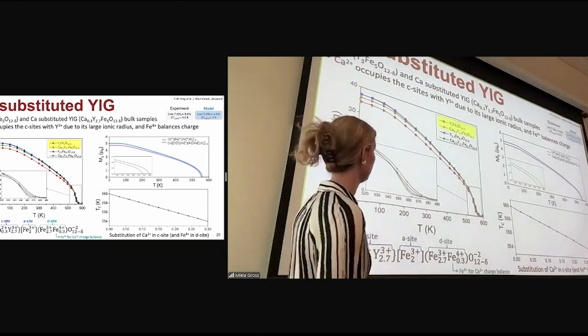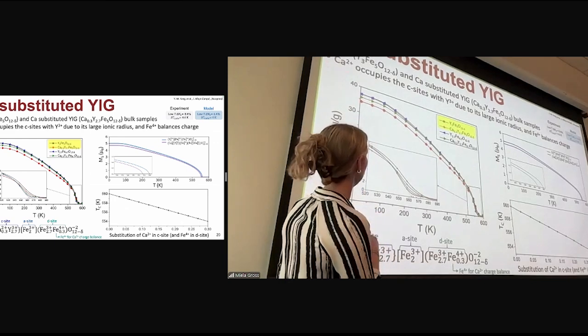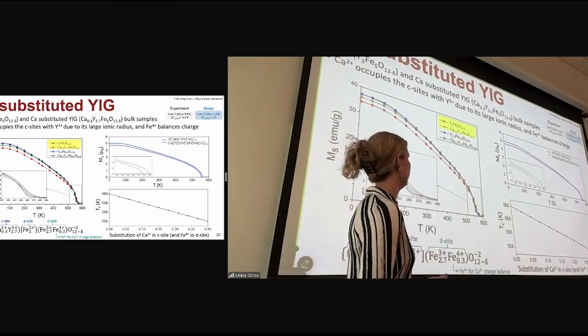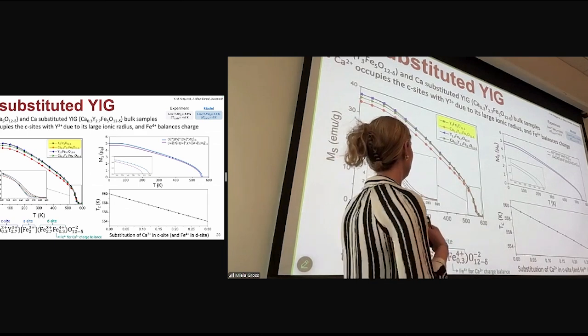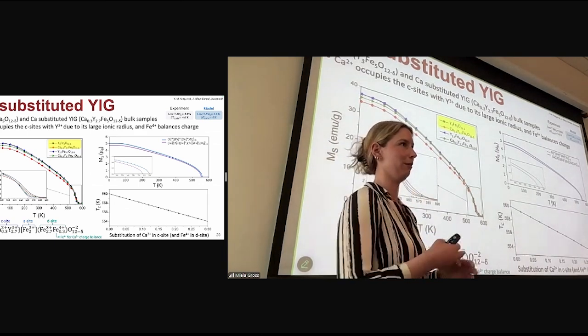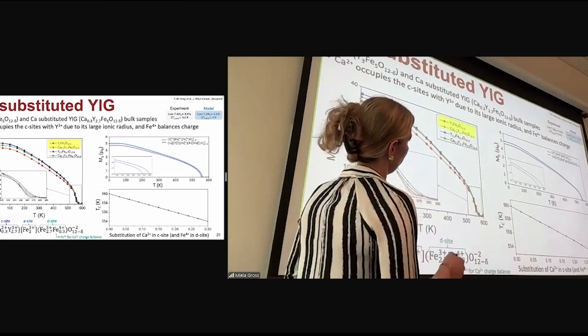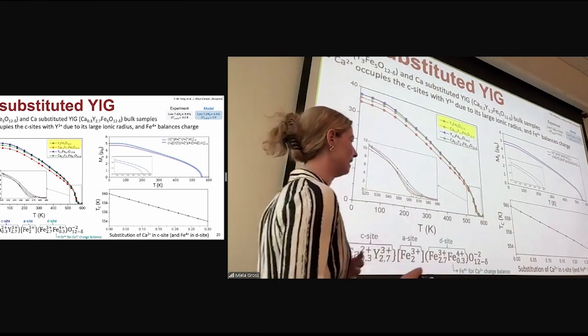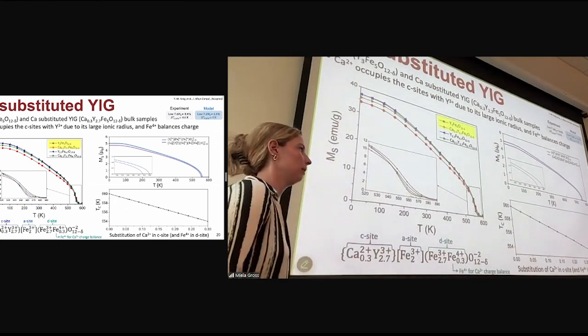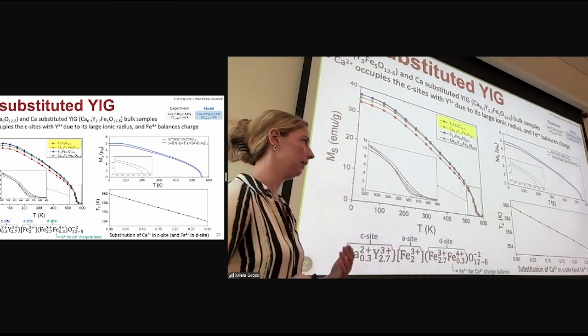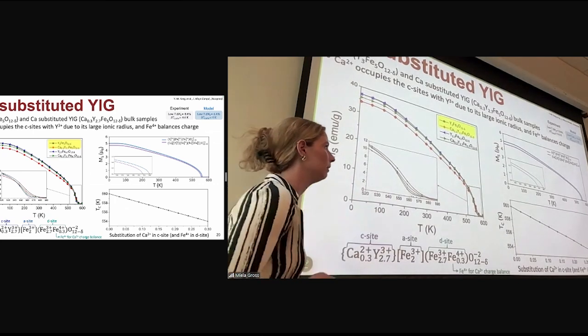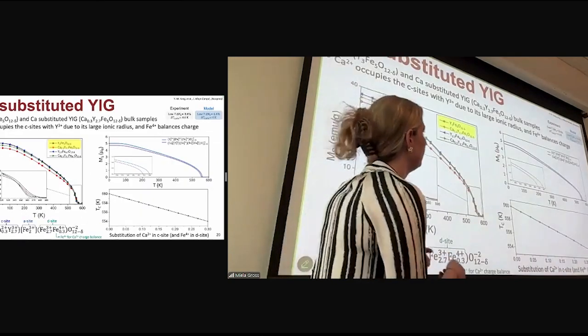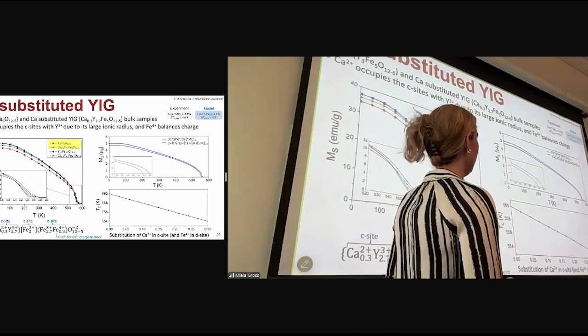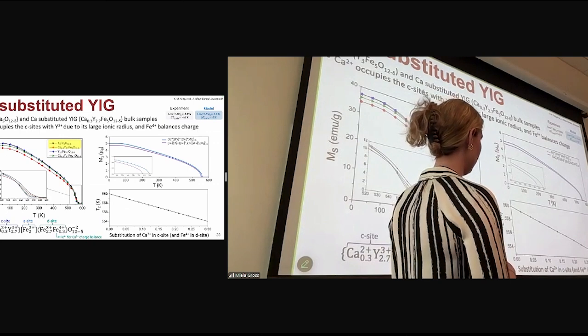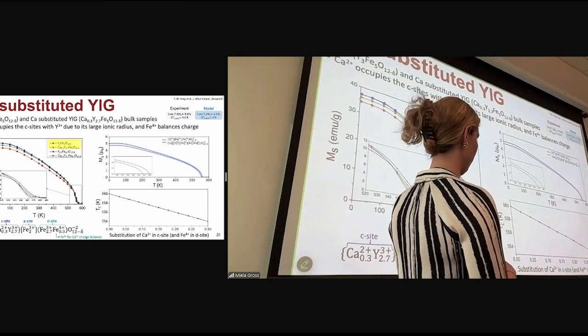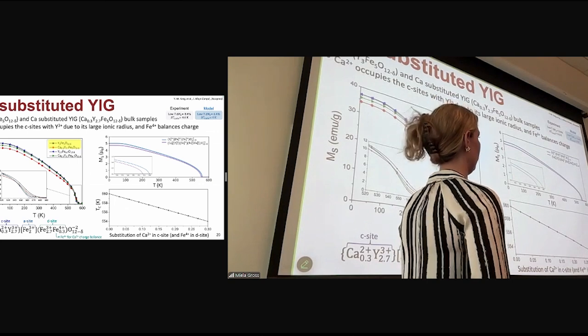So we had a hypothesis that calcium likes to be in its 2+ state, and again, it occupies the C site with yttrium, but that then leaves us with a bit of an off charge balance. So then there would be some iron 4+, probably in the D sites, to balance the charge. So we look to our model to model what the resultant M versus T curves would look like. And we see from our MS curves that there is a slight decrease in the MS from just pure YIG to the calcium substituted YIG, and also a slight decrease in the Curie temperature.